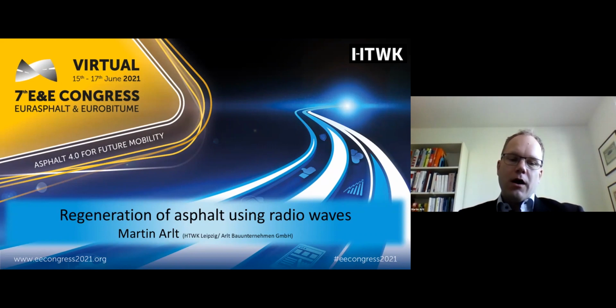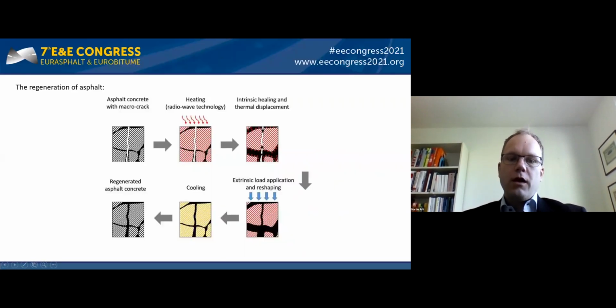Today, I'd like to show how the regeneration of asphalt using radio waves could enhance the maintenance of roads. First of all, I'd like to present what is to be understood under regeneration of asphalt. It is basically the combination of the intrinsic healing effects out of the heating of asphalt with radio waves, so the bitumen is mobilized and can flow into open cracks, and the extrinsic load application and reshaping of the thermally deformed asphalt to its original shape. So in the end, the asphalt is in the same shape and place as before.